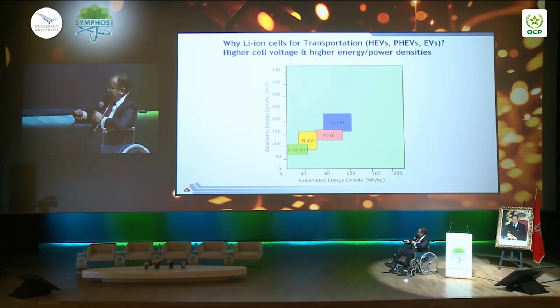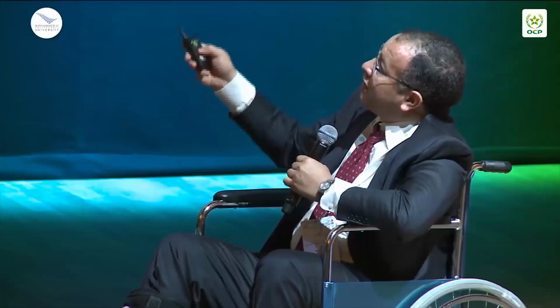Now, as I mentioned, lithium-ion is very attractive because it provides the highest volumetric and gravimetric energy density. In other words, you can make batteries smaller and lighter, yet very energetic. There is a big square here, which means the technology is very versatile. You can develop different cathode, anode, electrolyte, different systems, high voltage, low voltage, and so on. Unlike this system, where the chemistry is basically fixed and you just have some dopant to improve the performance. So there is an opportunity here.